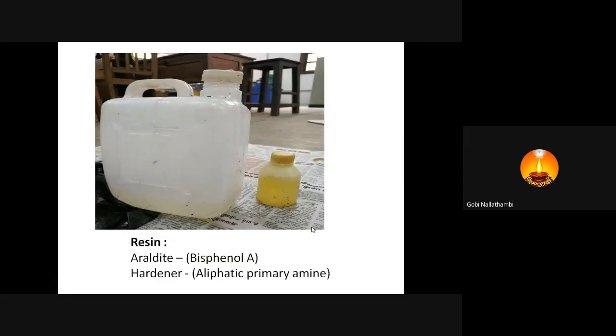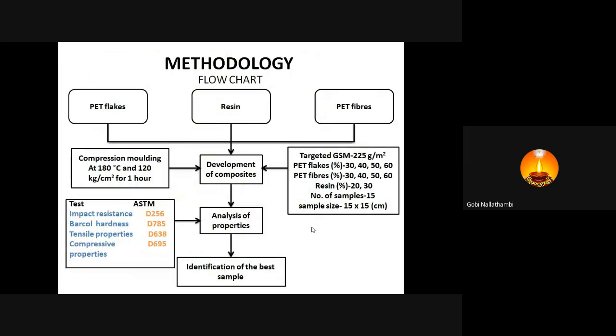Then the resin is Araldite, and a suitable hardener is taken. So this is our methodology for making the composite. For PET flakes, PET fibers and resin, our targeted GSM, grams per square meter, is 225. The flakes proportion varied from 30, 40, 50 and 60. PET fiber proportion varies from 30, 40, 50, 60. Then resin is 20, 30. Our idea is to minimize the utilization of resin and maximize the usage of flakes and fiber for making the composite.